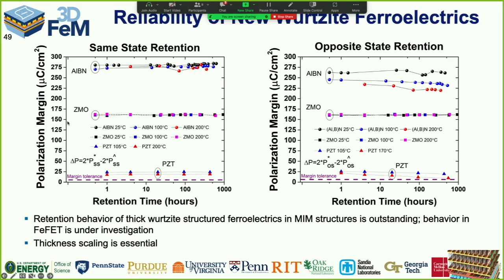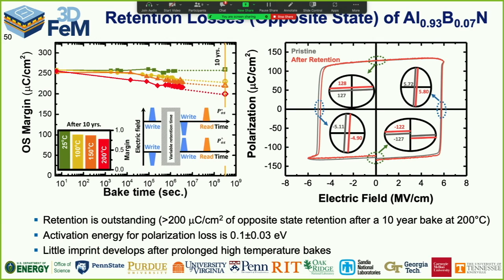You see the aluminum boron nitride, zinc magnesium oxide, we got signal margin to burn, and they're incredibly stable in the same state. And they're incredibly stable in the opposite state. We have baked these for 1,000 hours at 200 degrees C. In the case of the zinc magnesium oxide, we actually can't find a loss in polarization, which means that when we extrapolate out for aluminum boron nitride, we start to see a little loss. But we've extrapolated out to a 10-year same, 10-year opposite state measurement, and we still have 200 microcoulombs per centimeter squared to read. That's huge. Lead zirconate titanate, they call that bit failed at 5 microcoulombs per centimeter squared. So retention, we have solved that problem.